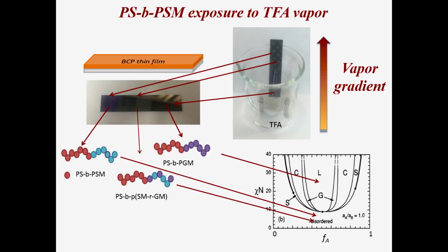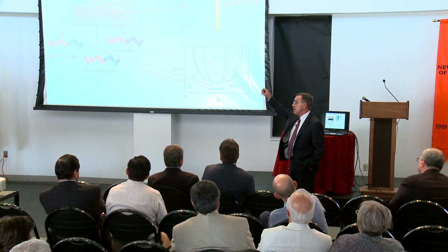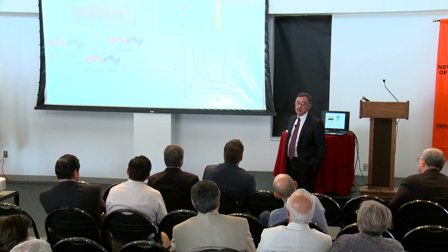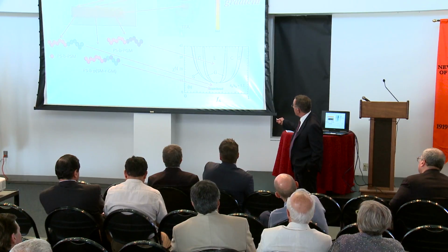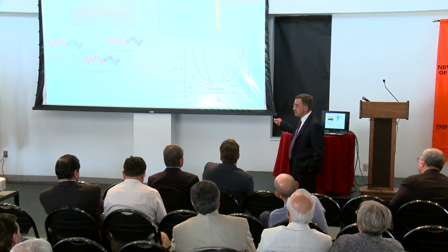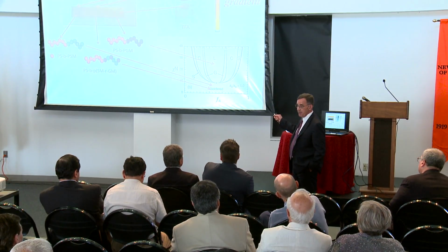Now, the reason that that's important is that this copolymer here is ordered. This isn't ordered. So I basically go from a point where I have ordered to disordered. And if I were to take this film and leave it there, or drop it down further into the beaker, then what would happen is this ordering front would move up the film.